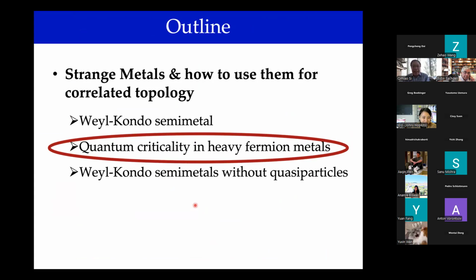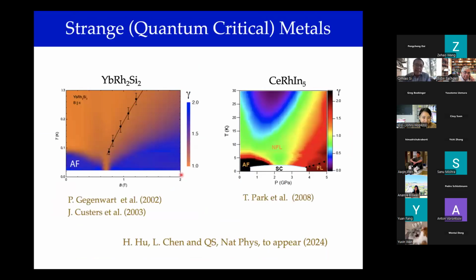I want to briefly outline the quantum criticality in heavy fermion metals, the strange metal aspects, to come together with the topology. And these have been studied for a somewhat longer period of time, although in the history of heavy fermion physics, this field is still a relatively young subject. And the strange metallicity is exemplified by this kind of temperature versus control parameter phase diagram, ytterbium rhodium-2 silicon-2, this orange color portion of the phase diagram, and the 115 in this green portion of the phase diagram. They all happen in a quantum critical regime. They all have T-linear resistivity.